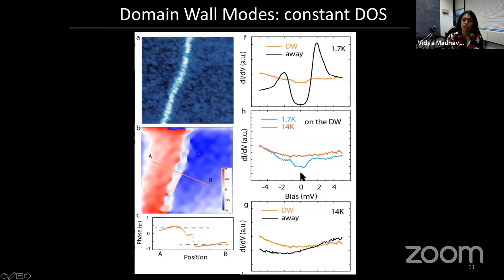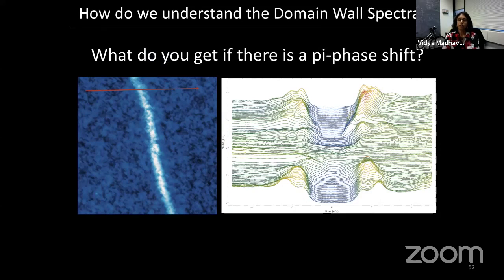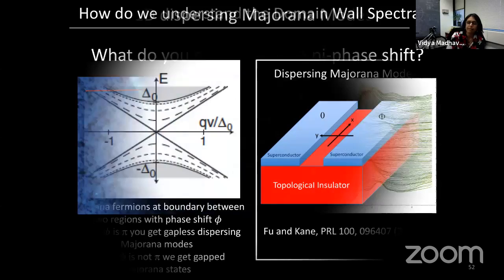So this feature is directly associated with superconductivity. This is the phase map that I was telling you about of the Fourier transform. If you look at the phase of the Fourier transform, then on the left-hand side and the right-hand side, you can see a pi phase shift between these two regions. In any case, the question is, what does it mean that you have this flat density of states?